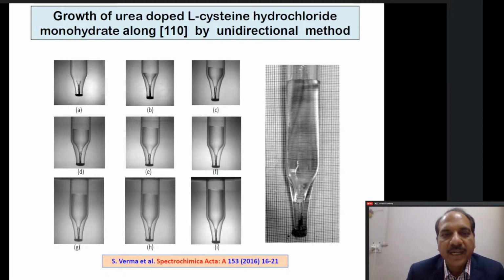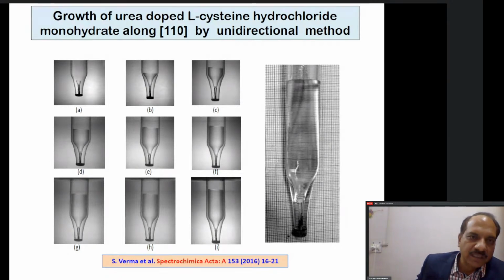We also do online real-time imaging of the growth process. So this was the small crystal which we had put. If you see the image marked as A, this is the starting of that growth. And then every day we used to record this, because there was a camera fitted in the chamber. We used to record images every few hours, and then I have taken out these images every 24 hours, right?